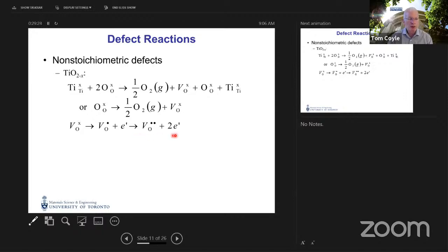Or in fact, it may give up both electrons. There may be very little attraction for those electrons locally adjacent to that vacant site in the lattice, in which case we can describe the case of both electrons moving to the conduction band, leaving behind at that vacant oxygen site a relative charge of +2.